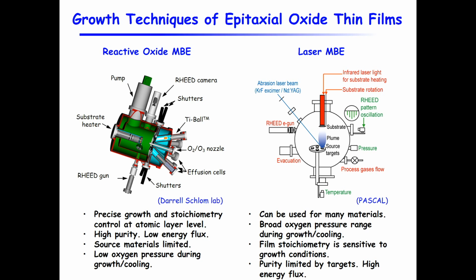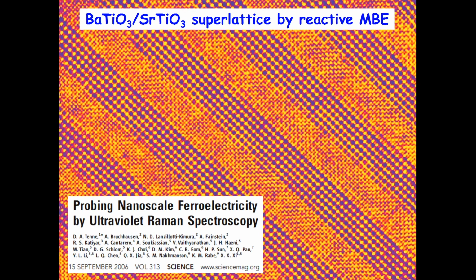And there are other issues, for example, the energy of the fluxes is higher than in the case of evaporation. But these are the two most successful techniques in making oxide films. And here are examples of the physics that all this capability allows people to do. Barium titanate, strontium titanate superlattices. This is a TEM image of a cross-section sample. And you can see that these are precise to the unit cell level. And so you can grow very high quality samples to study properties like ferroelectricity at the nanoscale.